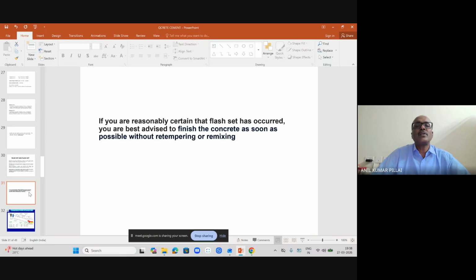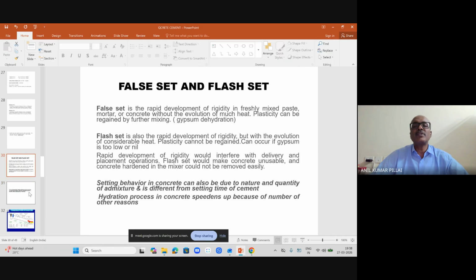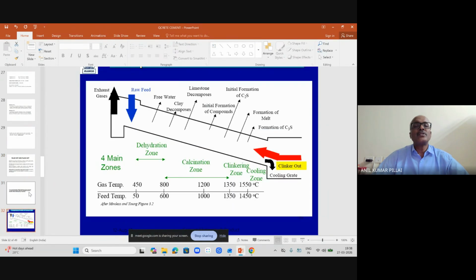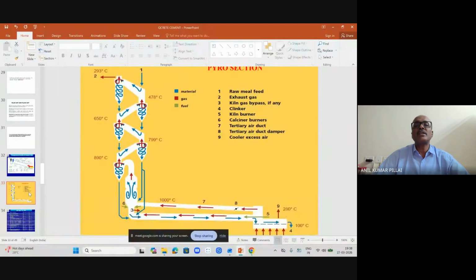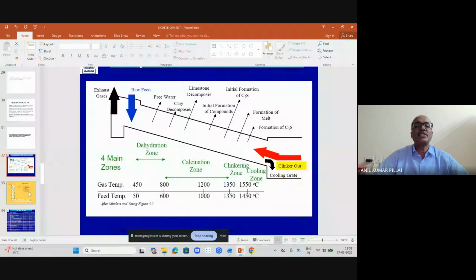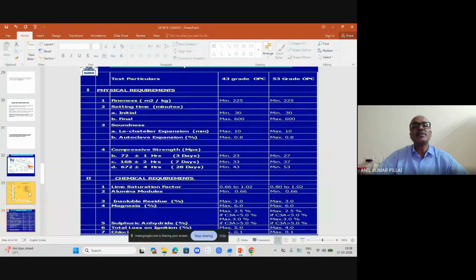which sometimes happens. So if you are reasonably certain that the flash set has occurred, your best advice is to finish the concrete as soon as possible without retempering or remixing, because plasticity cannot be regained. And just to give you an idea, taking you back to the manufacturing process, it is very important that the temperature is maintained at various stages while the clinker is coming out.